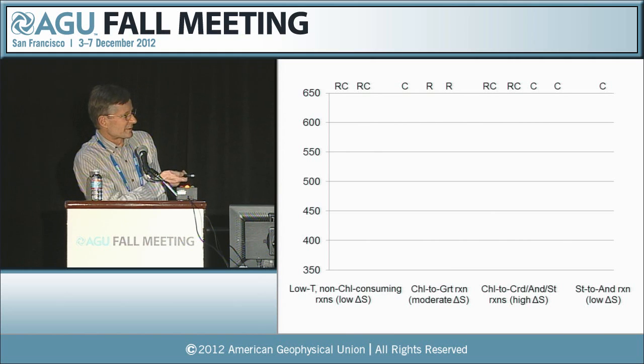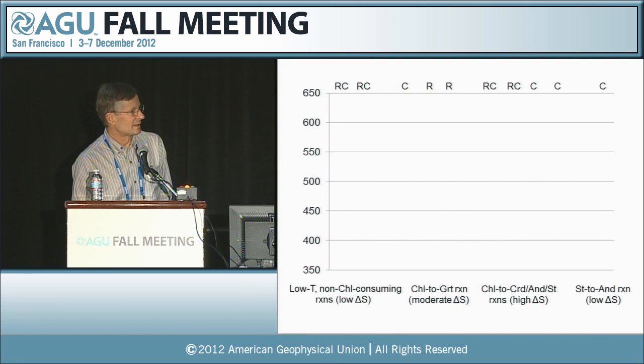I'm looking at 4 different types of reactions along the bottom here. These are low temperature, non-chlorite consuming porphyroblastic reactions. These typically occur in aluminous bulk compositions. Here's the chlorite to garnet reaction. This set is chlorite to either cordierite, andalusite, or staurolite, which is the highest entropy reaction. And then this last one here is the staurolite to andalusite reaction, which is a low entropy change reaction.